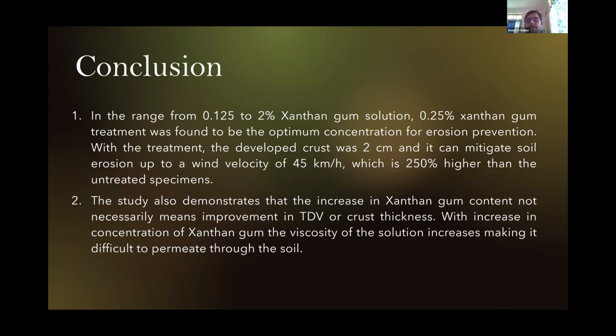This study also demonstrated that an increase of xanthan gum does not necessarily mean it will increase the wind erosion resistance, as is shown in the UCS test. There, they claim that increasing biopolymer content improves the strength accordingly. But that doesn't happen in the case of the wind erosion test.